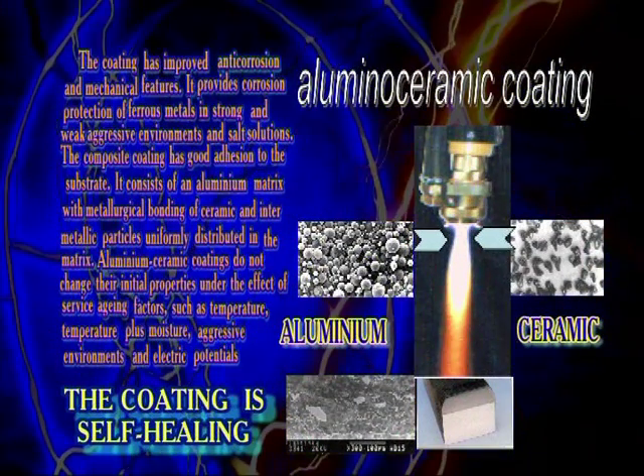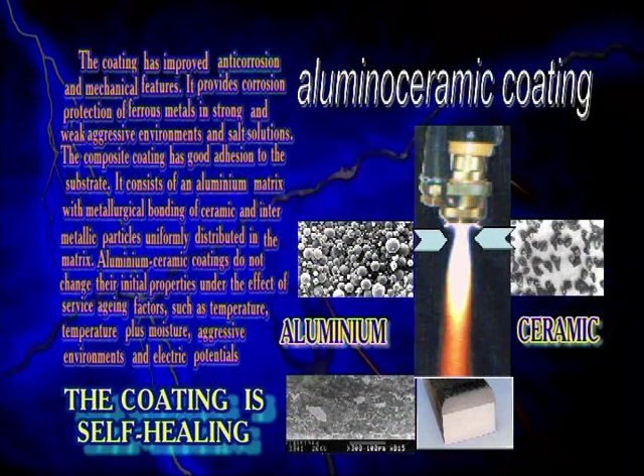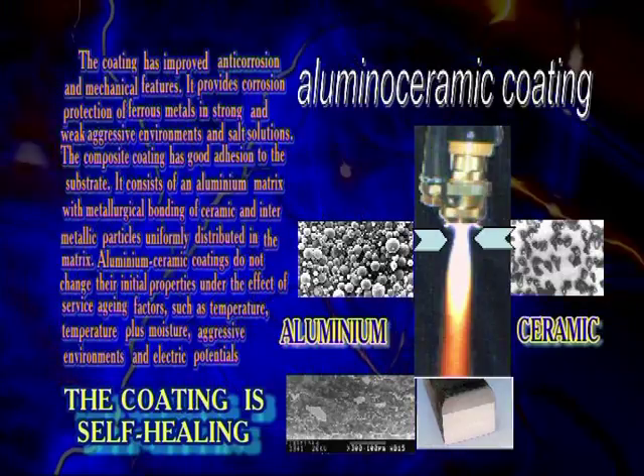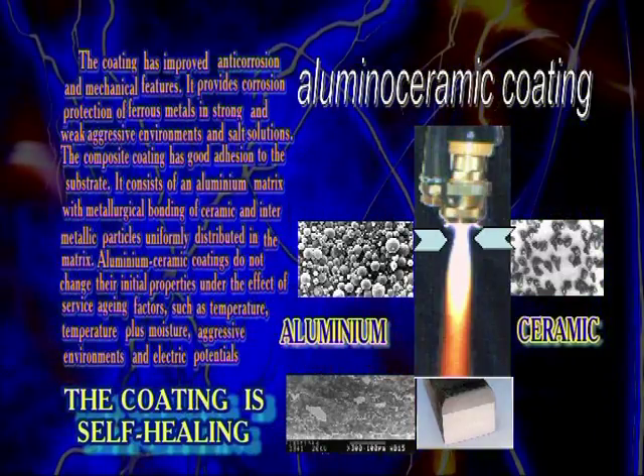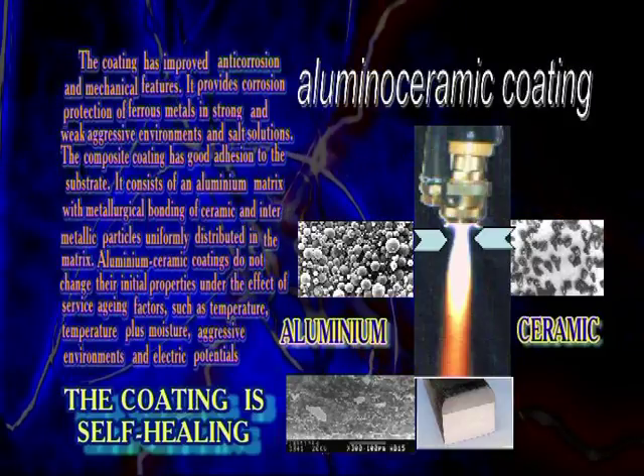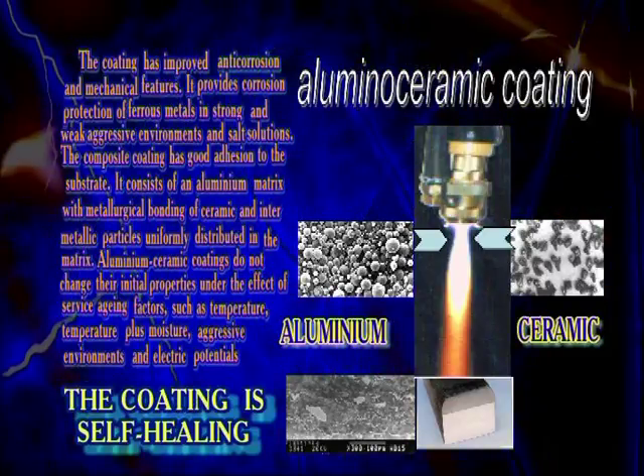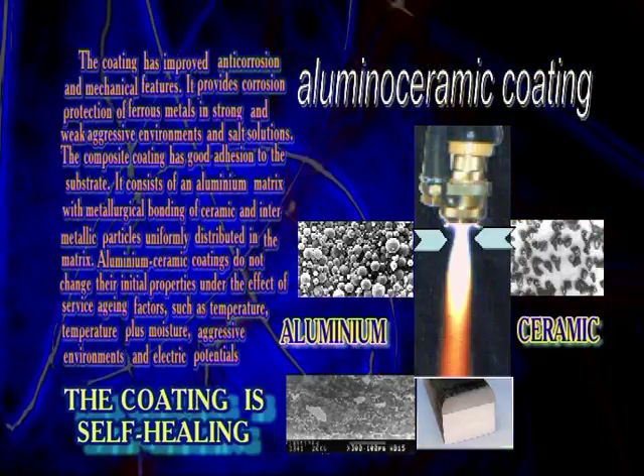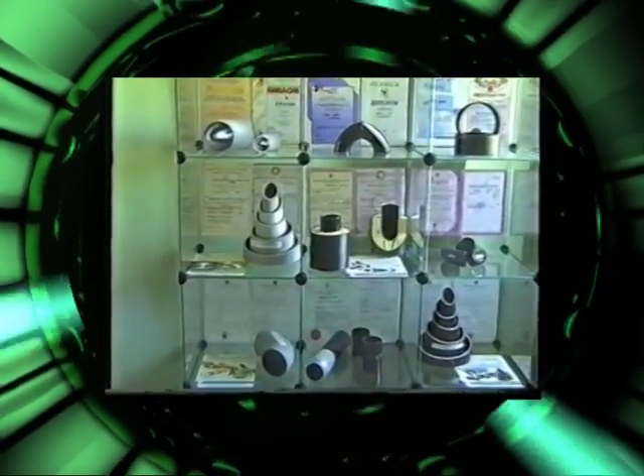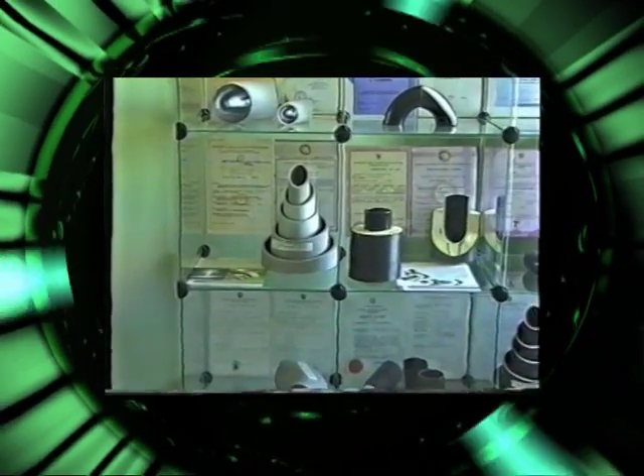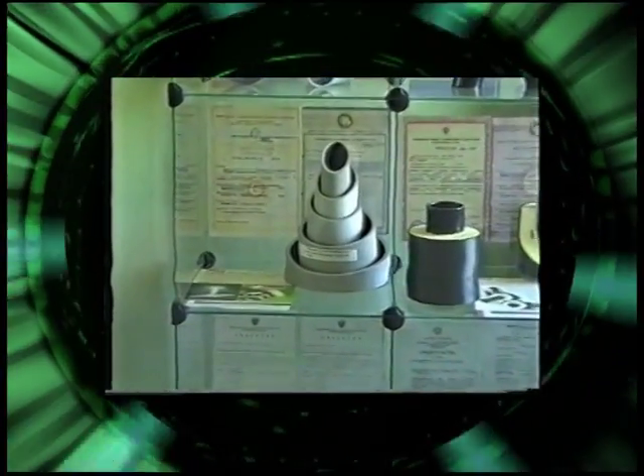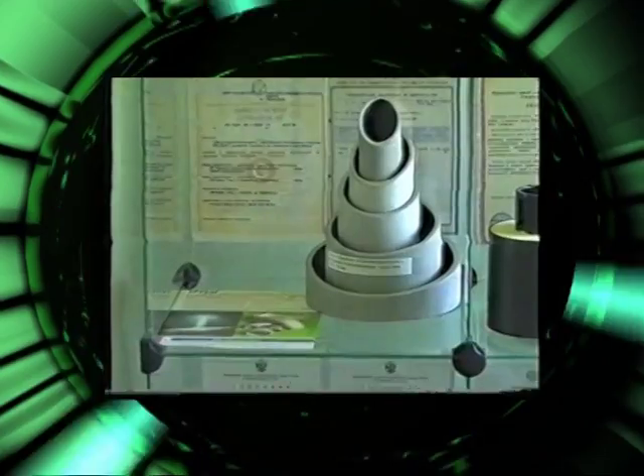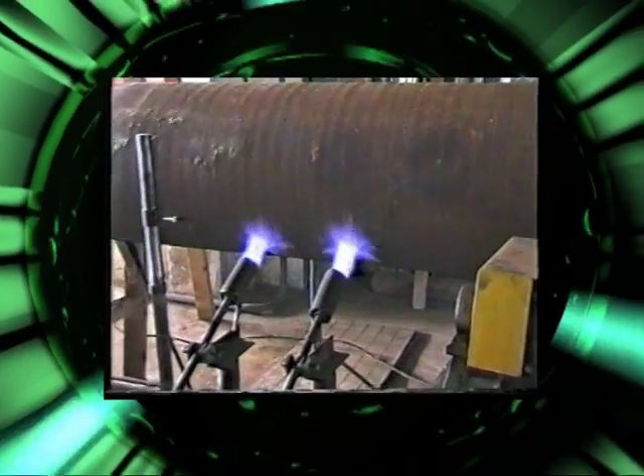Aluminum-ceramic coating is designed for corrosion protection of ferrous metal structures that operate in weak and strong corrosive environments. These are ship bodies, sea oil platforms, and pipelines. The composite coating comprises aluminum matrix with homogeneously distributed and metallurgically coupled ceramic particles. It has low porosity of 0.5% and is well adhered to the substrate. Its tensile strength is 35 MPa. The coating is produced by high-energy plasma spraying.